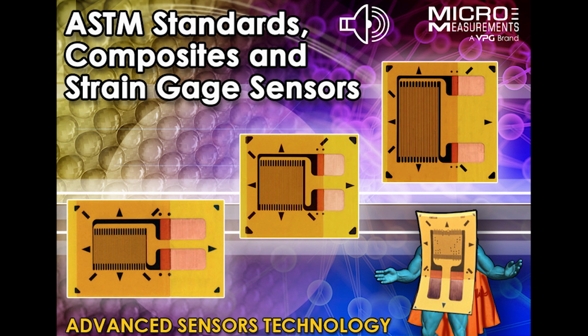And again, we're talking about a 250 type size gauge, 350 ohm resistance minimum. And the reason for the resistance, in anything really composite or plastic, is that because they're insulating materials, there's a chance that the actual gauge could heat up. Having a 350 ohm gauge helps reduce some of that. Yep. It allows you to have a little higher excitation in some cases if you need it. You try to be between 1 and maximum probably 5 volts, but I would probably say 1 to a half volt is where you're going to be. So in a lot of cases, using 120 ohm is totally not recommended, because then you have a heating problem, and then you get thermal output and things that you don't need in your testing.